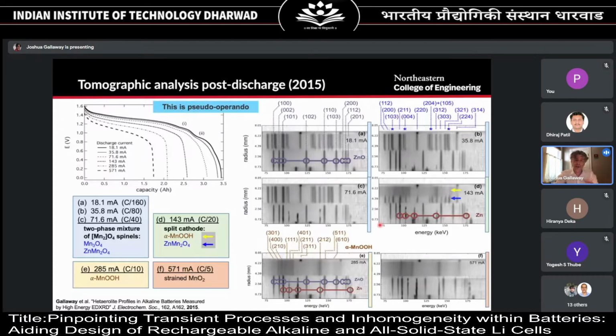Then what we did was look at the discharge curve of these types of batteries. Here this red curve is a discharge curve, and there's a dip in the curve right here, which you may or may not be able to see. But the dotted line shows the first derivative, so you can see the first derivative changes right there. So that's an inflection point in the curve. And no one had ever talked in the literature before about what that inflection point was.